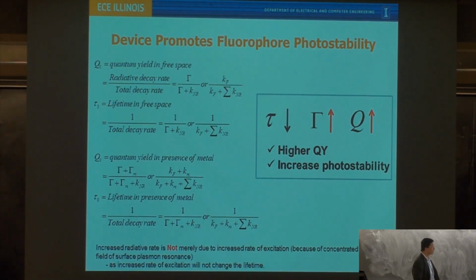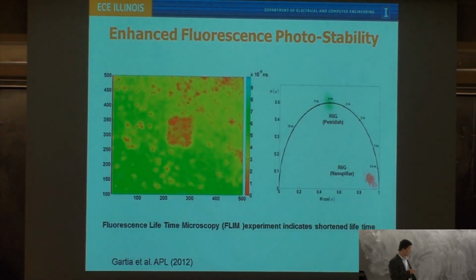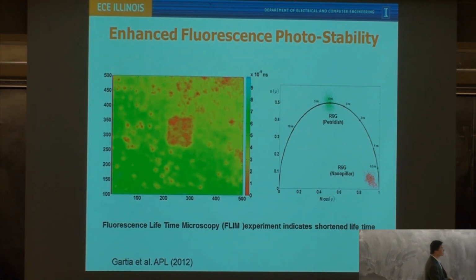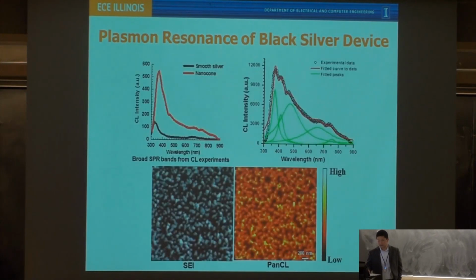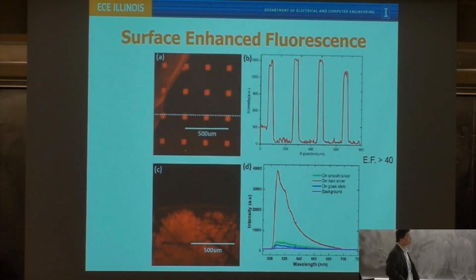How far into the space? For this study, we only study molecules adsorbed on the surface. In principle, does it have to be within a certain distance? Yes, they have to be within 100 nanometers above the surface. So you see only really the interaction with the membrane of the cell.